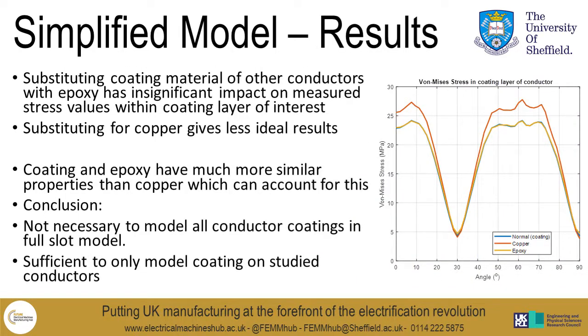So you can see the results on this slide. You can see that changing the coating layer for epoxy has very little impact on the resultant stress in the other conductors. However, using copper gives less ideal results. As a result, it's preferable to replace the material with the epoxy, as they are relatively similar materials. This is helpful when we come to model the entire slot, as it means we don't have to put the very thin conductor coating layer on every conductor. We only have to apply it to the conductors where we're directly interested in measuring the stress, which simplifies the model.